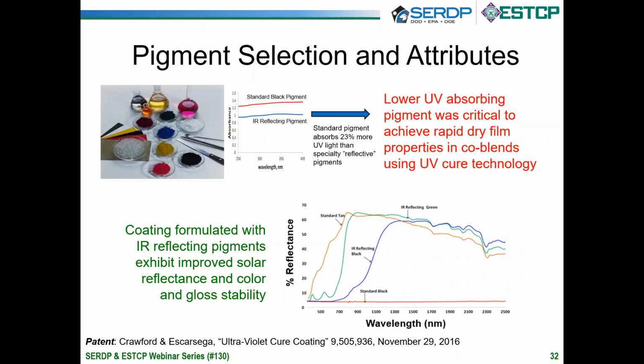The key point here is that the selection of pigment types can influence how effectively we can influence the UV and the near IR, and in particular to create low solar absorbing coatings. The impact reduces the absorption of photons that are harmful to damaging the resin system, and also results in low surface temperature. And so the combination is a longer life for the coating itself.